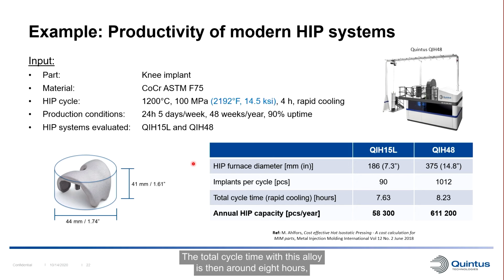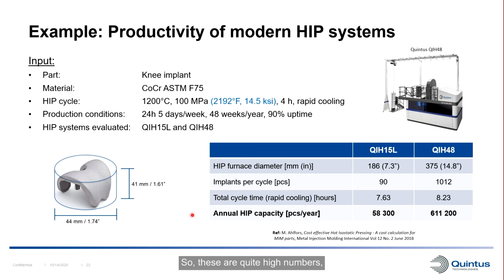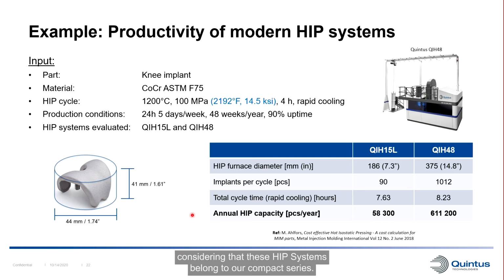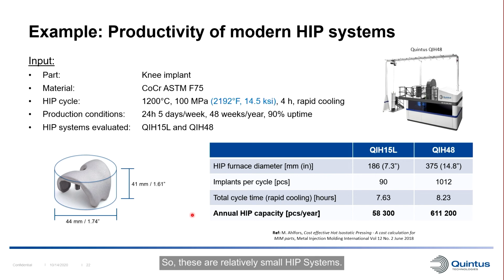The total cycle time with this alloy is then around 8 hours, with a little bit longer time for the larger system. And this is calculated with the rapid cooling. If a HIP system without rapid cooling would be used here, the cycle time would be close to double this number. So looking at the annual HIP capacity with these systems for this part, we get around 58,000 implants per year in the QIH15L. And with the QIH48, we get around 611,000 implants. So these are quite high numbers, considering that these HIP systems belong to our compact series. So these are relatively small HIP systems.